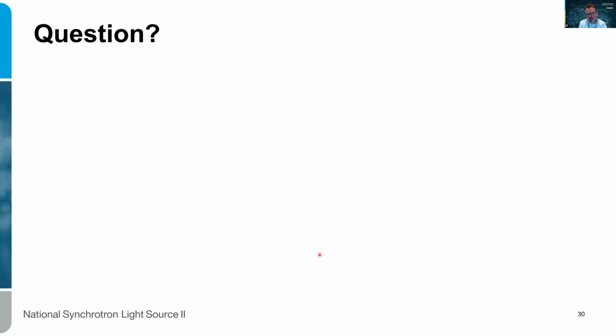Matthew, it's an excellent remark. I want to say that indeed there is this assumption of smooth transitions with MCR, but it doesn't mean you cannot treat other kinds of data with this. For instance, there's work that Dennis Lesher, the Beamline scientist at ISS, has done with one of the users who had a large set of 100 spectra of cerium oxide that contained cerium-3 and cerium-4. Because we had all the variations of this, we could stack those spectra so there would be smooth transitions and identify the two components that were not quite similar to pure cerium-4 plus and cerium-3 plus.